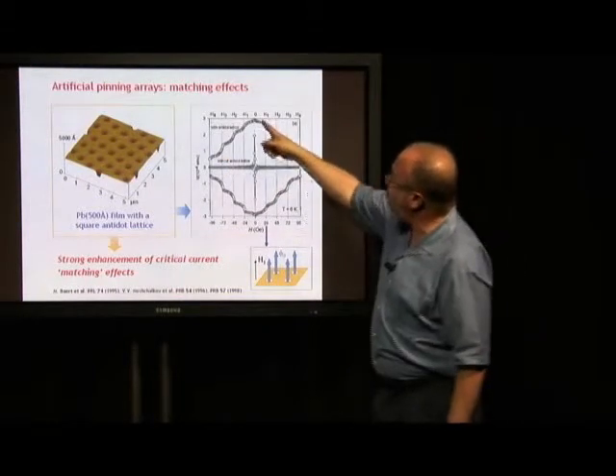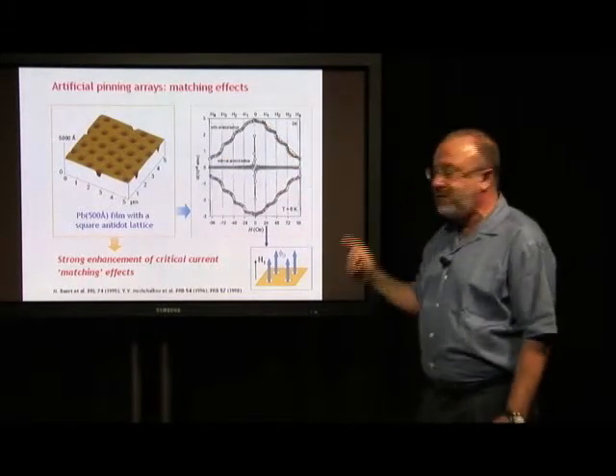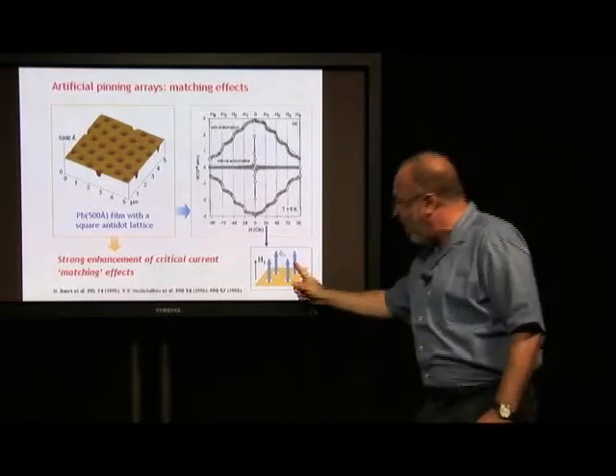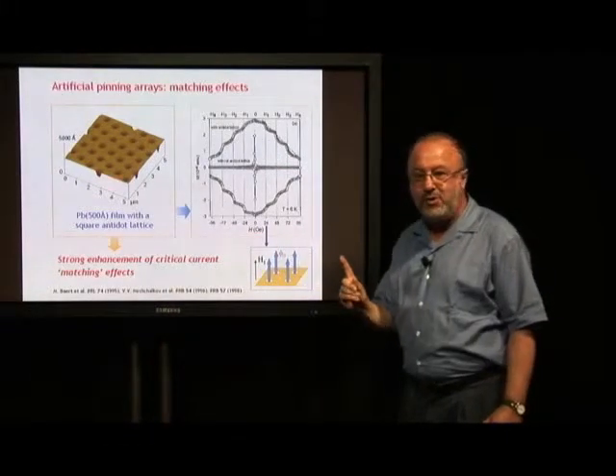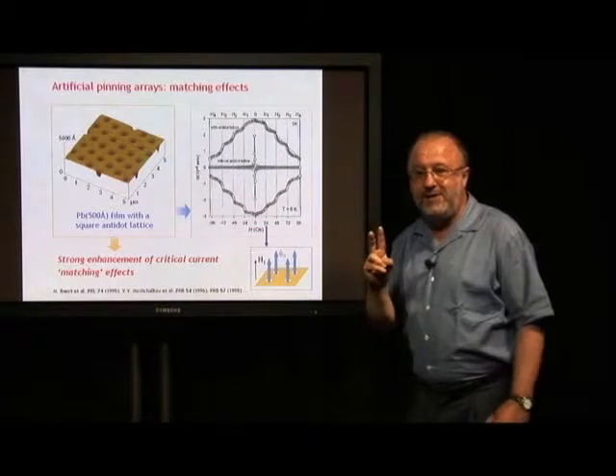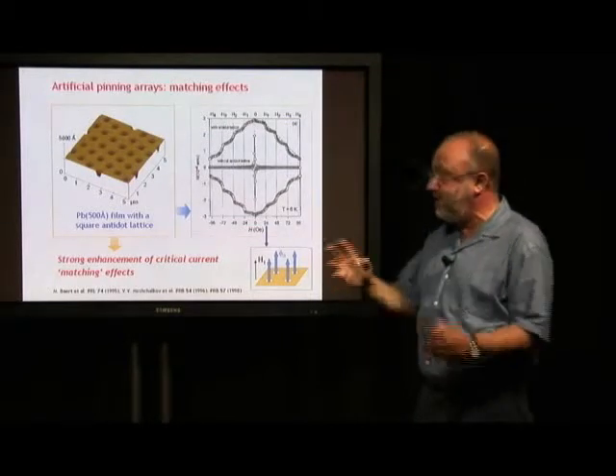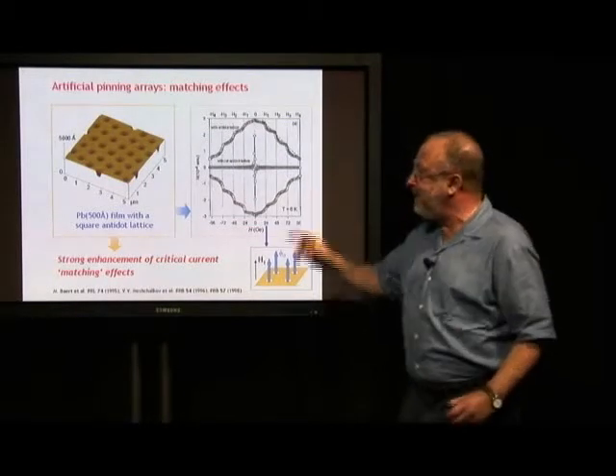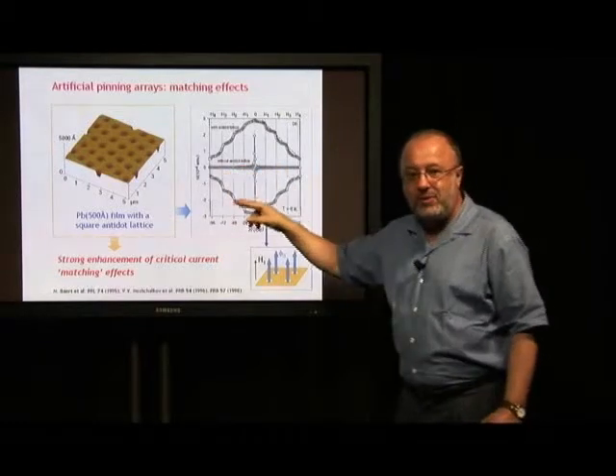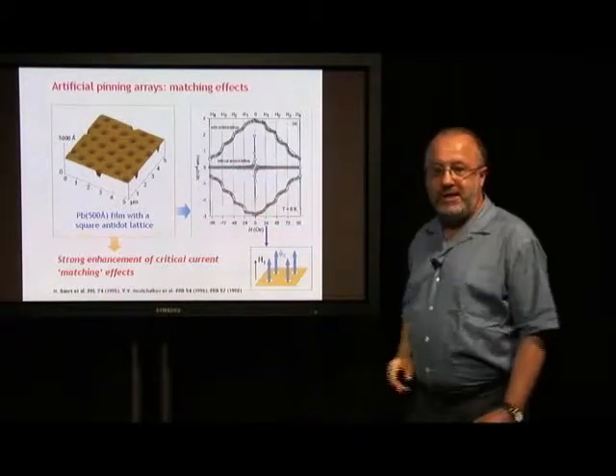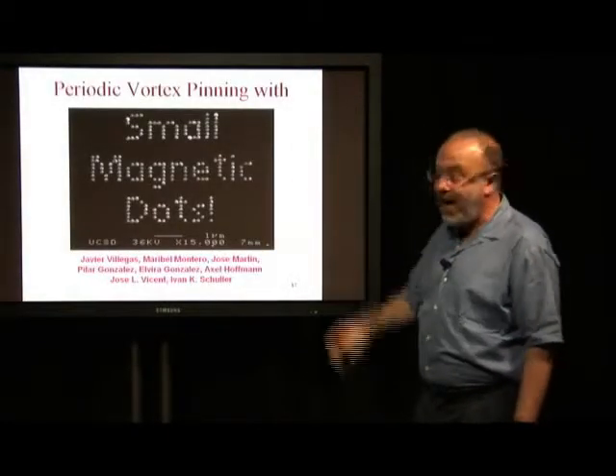And it turns out that each one of these kinks here is related to the situation in which there is either one vortex entering into each one of the holes, or two vortices entering into each one of the holes, or three vortices. So there is some kind of a matching effect between the lattice of the artificially drilled holes and the vortex lattice. Now, I picked up on this.